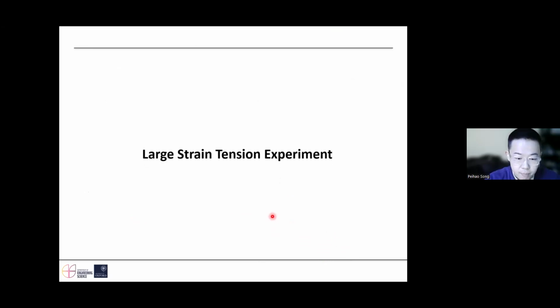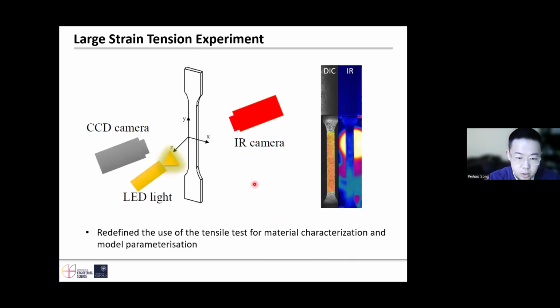Now, I started my PhD by doing large strain tensile experiments, which are very relevant to industrial demand. Everyone uses that to examine their material. In my test, the CCD camera was put in front of the sample and the infrared camera at the back, which provide me with the strain mapping and the displacement mapping. And the infrared camera gives me the temperature rise mapping.